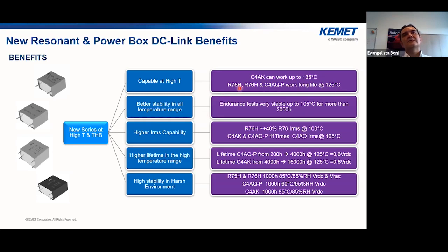But this characteristic to work at high temperature means also that these series are more stable at lower temperature. So also at 105 degrees, these series are really stable for a lifetime more than 3,000 hours and high voltage level. But what is important also is the power density. So they can work at higher ripple current. They can show higher ripple current withstanding. So we said that R76H is more or less 40% higher than the standard R76. C4AK, C4AQ-P can work up to 11 times, 12 times as a standard C4AQ.